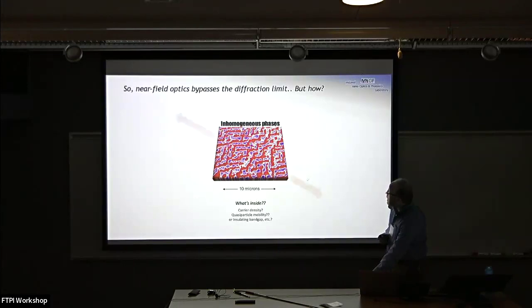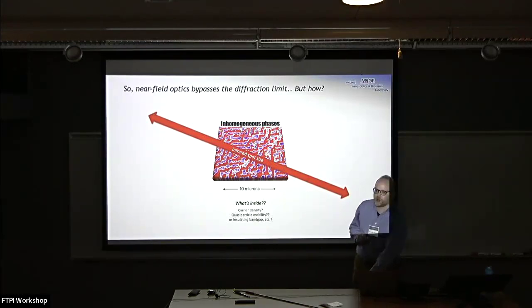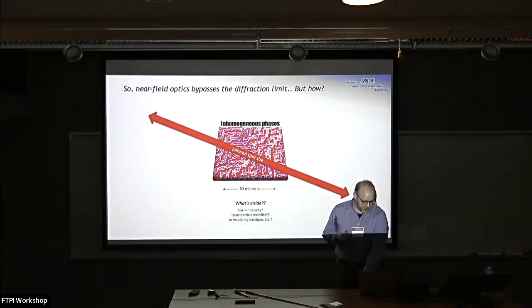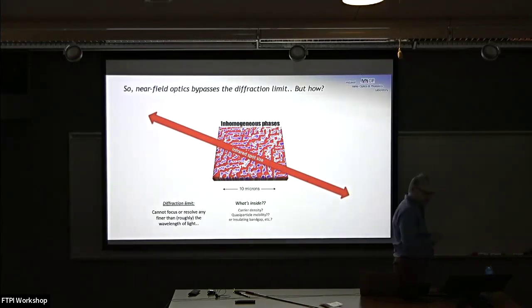So we should remember that the images that I've shown you are about 10 microns in size, but we're probing these materials with low energy light. And the materials distinguish themselves at low energies. Our Mott gap in our V2O3 is about an eV or so. So we certainly have to probe at low energy.